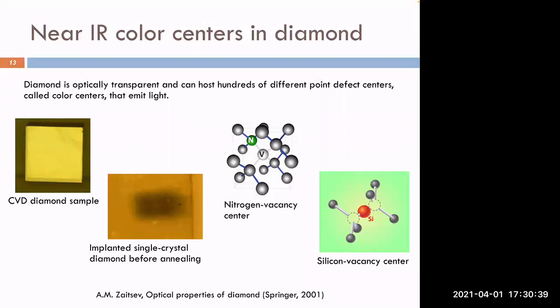So typically what you do is that you have an artificial diamond sample that you create by chemical vapor deposition. So this is a standard fabrication technique that is applied to many different material systems and also to diamonds. So essentially you take a substrate. This substrate can be made of silicon, and then you get polycrystalline diamond on it because of the lattice mismatch. Or you can take a diamond sample that you create by high pressure, high temperature techniques, and then you grow the CVD diamond, and this is single crystalline.